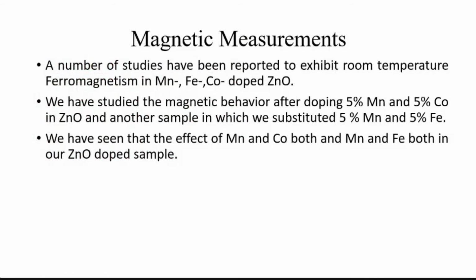Here, what we are observing is in my sample, the magnetic measurements. A number of studies have been reported to exhibit room temperature ferromagnetism in manganese, iron, cobalt doped zinc oxide, and we have studied the magnetic behavior after doping 5% manganese and 5% cobalt in zinc oxide, and another sample in which we substituted 5% manganese and 5% iron. So we have seen the effect of manganese and cobalt both, and manganese and iron both, in our zinc oxide samples.